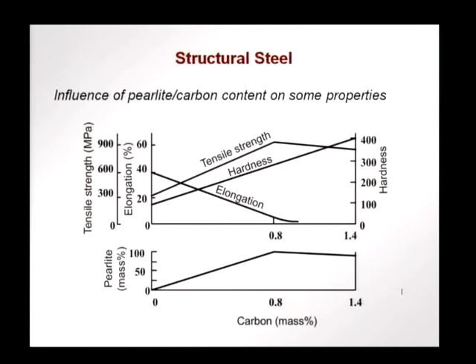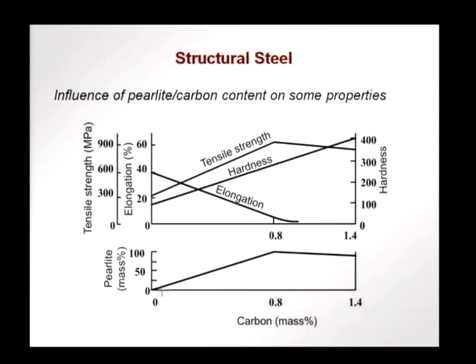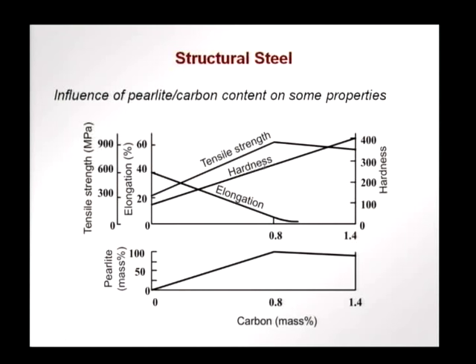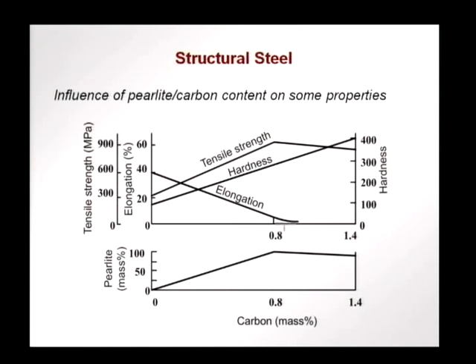Pearlite content is very important. As the carbon content increases and reaches about 0.8%, we have important repercussions in terms of mechanical properties. Tensile strength and hardness increase — so as the carbon content increases in the pearlite, the material becomes stronger and harder. However, it also becomes more brittle. We have elongation decreasing. Tensile strength can range up to 900 MPa, but elongation can decrease significantly as the carbon content increases in the pearlite, and when you have excess carbon it can become even worse.